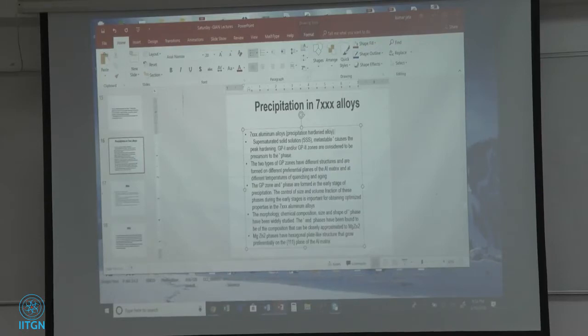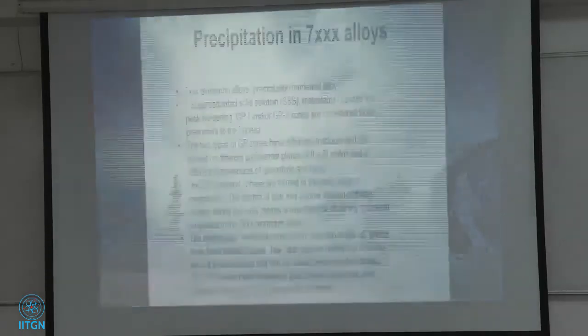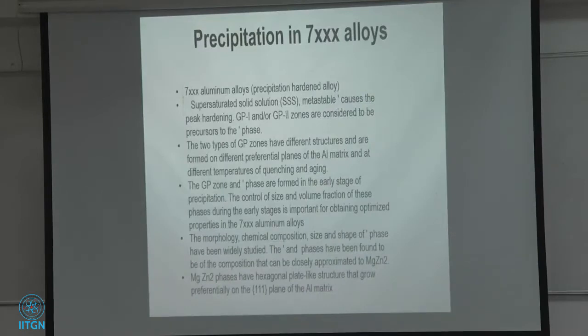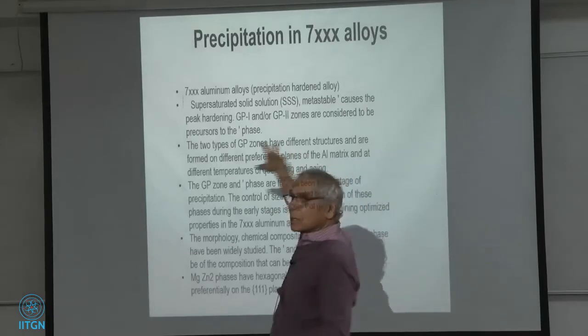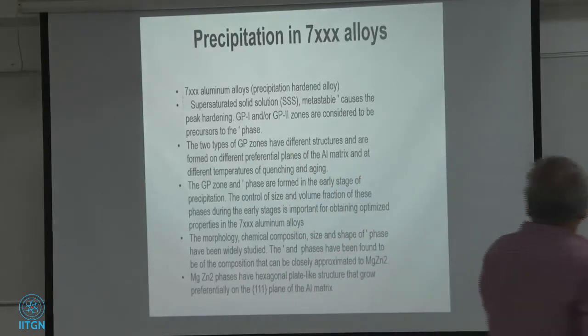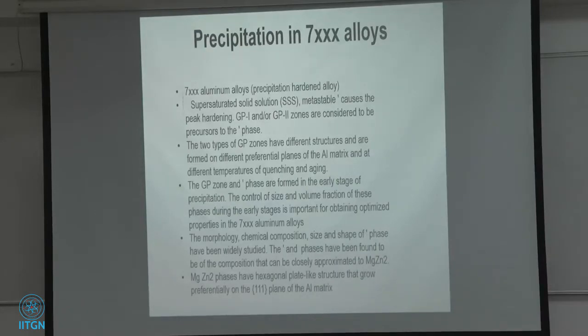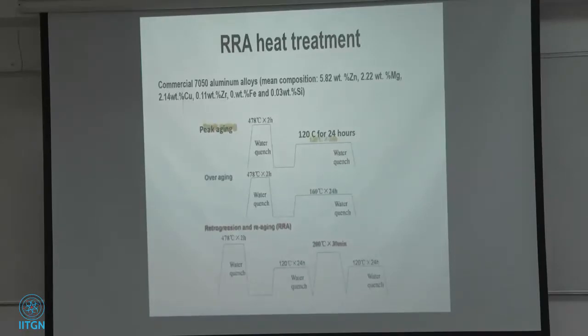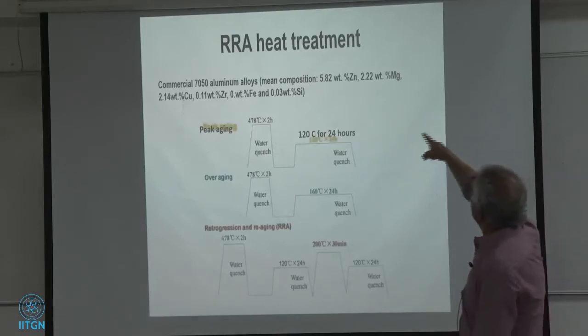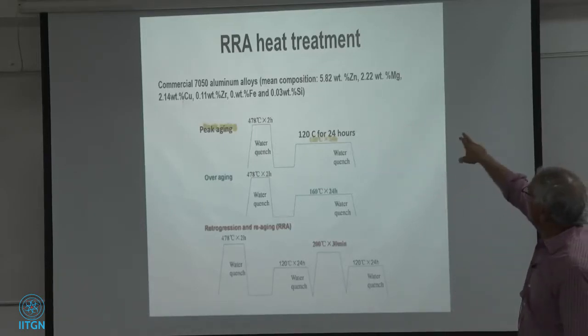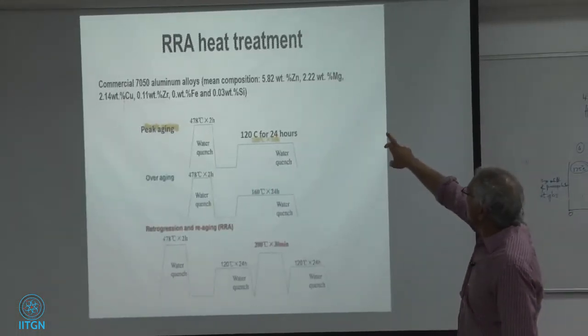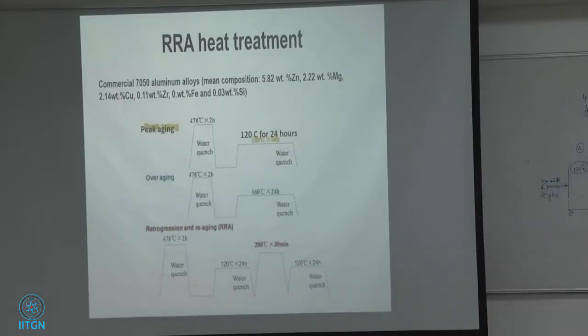So this alloy becomes harder, becomes stronger because of precipitates. That's how you do this, okay? So this also goes back to the question you were asking, right? So here is my supersaturated solid solution. That means all the elements, aluminum, magnesium, zinc, copper, those are the main elements. Aluminum, zinc, 5.8. Of course, it won't be exactly the same, but a little different. 2.22% magnesium, copper. As long as you remember it's an aluminum, zinc, magnesium, copper alloy. That's enough. Okay?